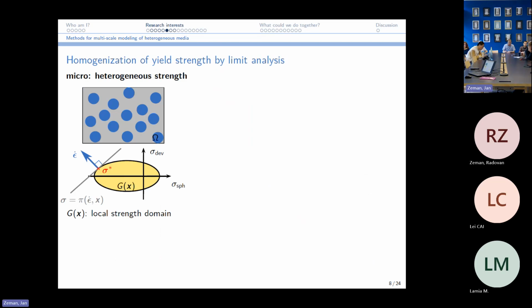Then I worked also on the homogenization of yield strength, in the context of perfect plasticity. So the idea is you have a heterogeneous microstructure, with phases having their own local strength domain. So maybe you have more ductile parts and some parts which are less strong. You would describe at the microscopic point each strength domain by some G of x function, where x is the position.